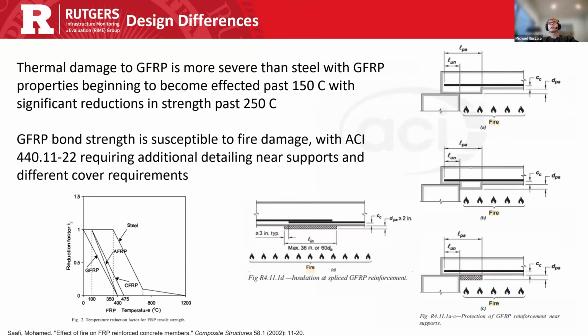Another thing to consider is the differences in thermal design. Our GFRP is a little bit more sensitive than steel. It begins to become affected at 150 C with significant reductions in strength past 250 C. You can see in the bottom left the reduction factor in strength. You can see steel leads that graph, having high resistance to thermal damage. So this becomes relevant in fire, for example, in a bridge deck or an overpass. If there is, let's say, a truck fire or car fire, this can become very relevant to that structure.